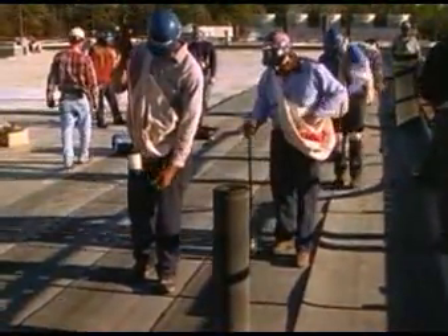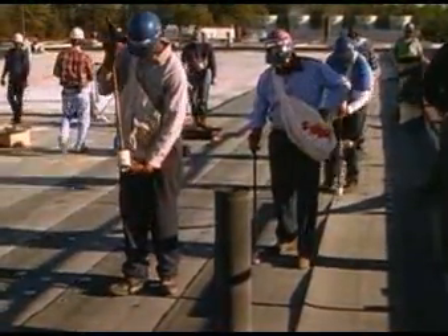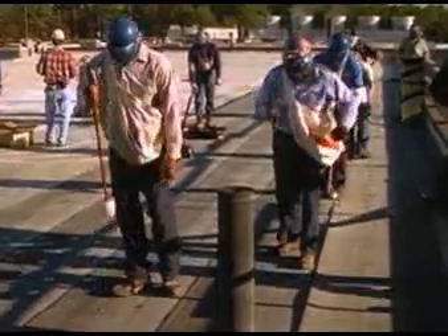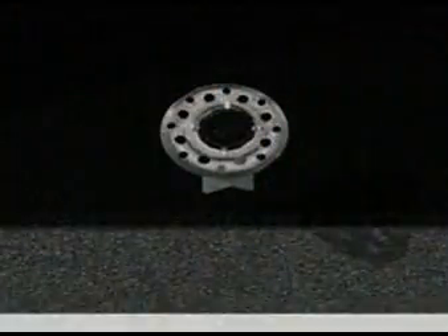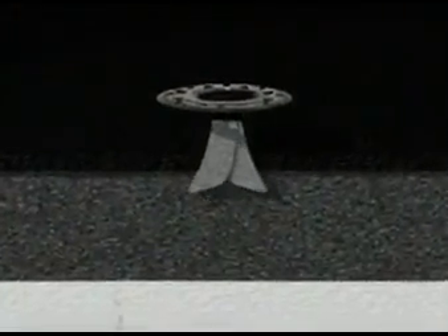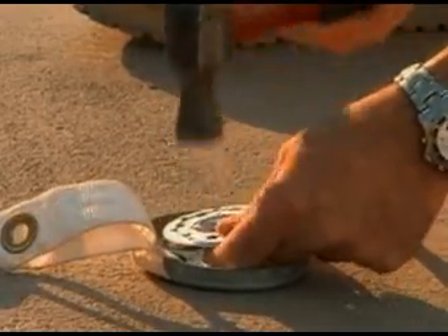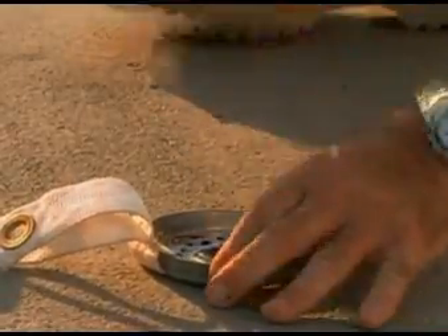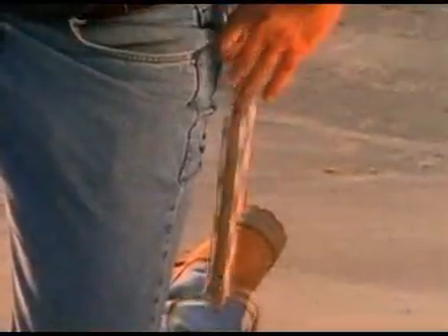A base sheet is mechanically attached to the finished lightweight deck with specially designed NVS fasteners. The fasteners have a two-piece stem that spreads when driven into the NVS concrete, producing an inverted wedge. This design offers withdrawal resistance of more than 40 pounds of force per fastener at the time of installation. Withdrawal resistance increases with age.